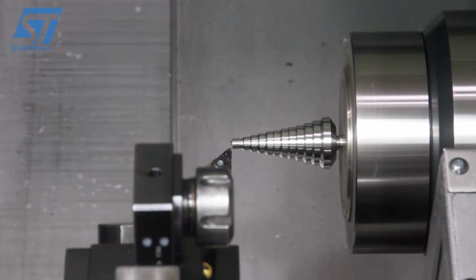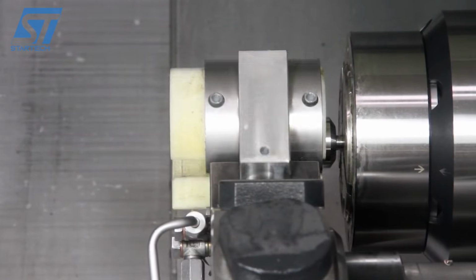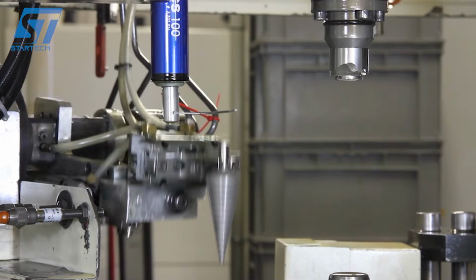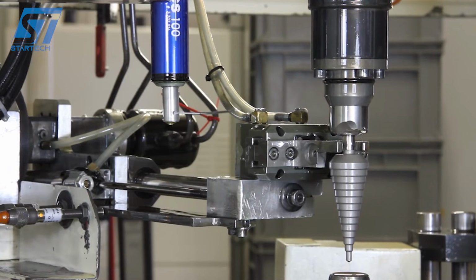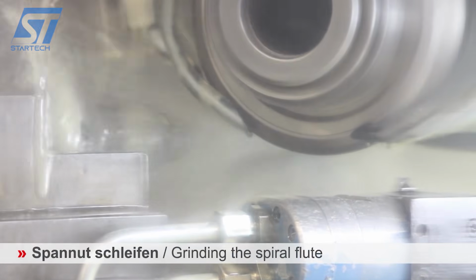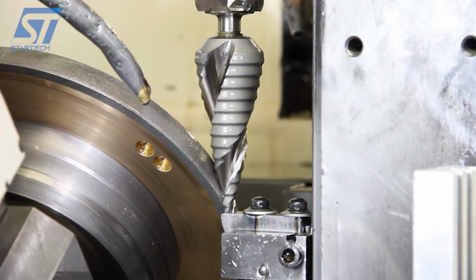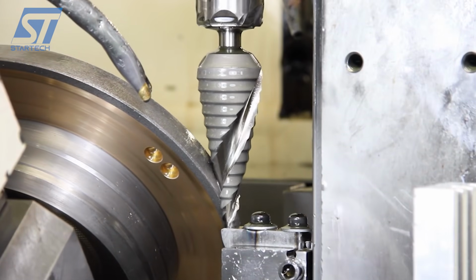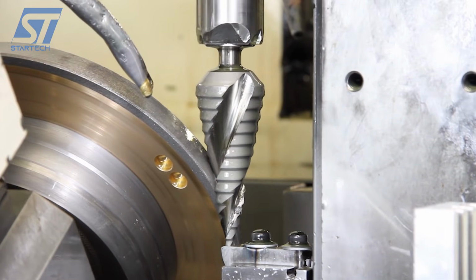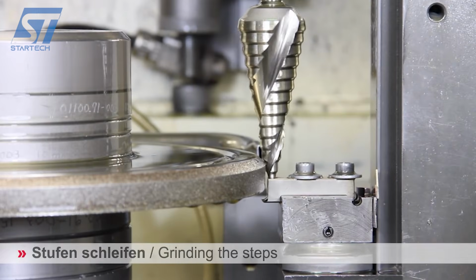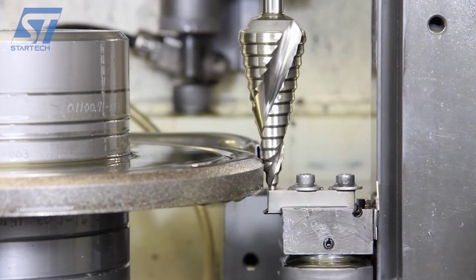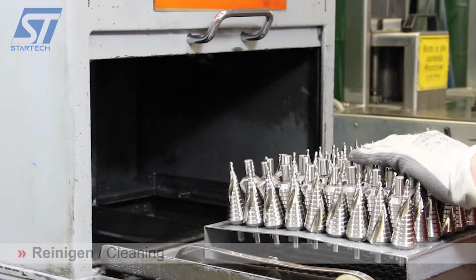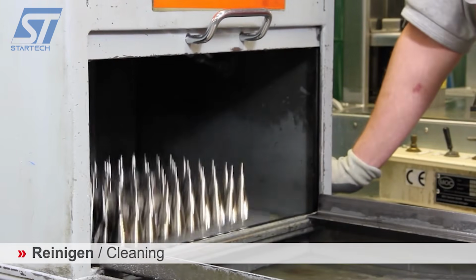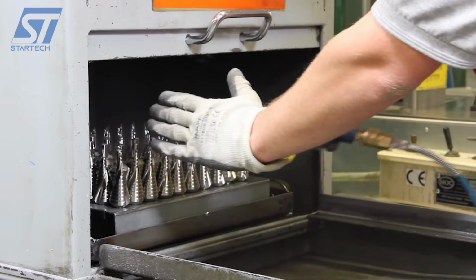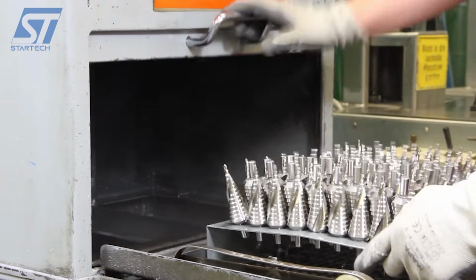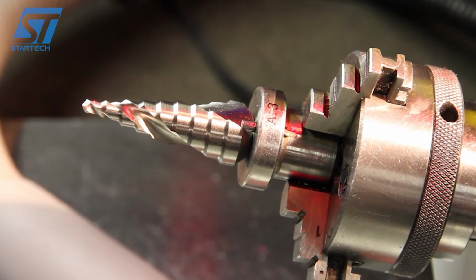Here's where it gets really impressive. With Ruco's high-performance step drill, the flutes, those spiral channels that clear chips away during drilling, are actually ground directly into fully hardened material using a CBN grinding process. CBN stands for cubic boron nitride, one of the hardest materials known to man, second only to diamond. Grinding hardened steel with CBN wheels allows Ruco to achieve sharper, cleaner cutting edges that would be impossible to produce any other way. After grinding, each bit goes through a surface treatment process to reduce friction and extend tool life. Then comes the marking stage, laser engraving the size steps directly onto the body of the bit with surgical precision. The result? A step drill bit that cuts clean, stays sharp, and earns its place in any serious workshop.